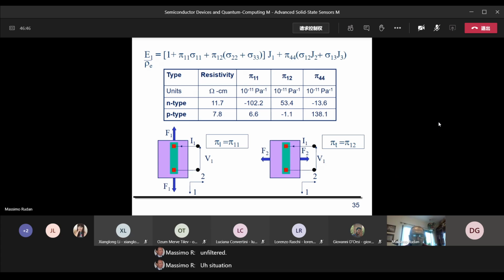situation. Obviously, if you look at the formula on top, in this case, you have that the only component of the stress tensor that has been applied is sigma 1,1. So all the other components of sigma are 0. Okay, so you measure the field by dividing the voltage by the length. The current is prescribed, okay, and the resistivity of the unperturbed case is given, so you measure pi 1,1.